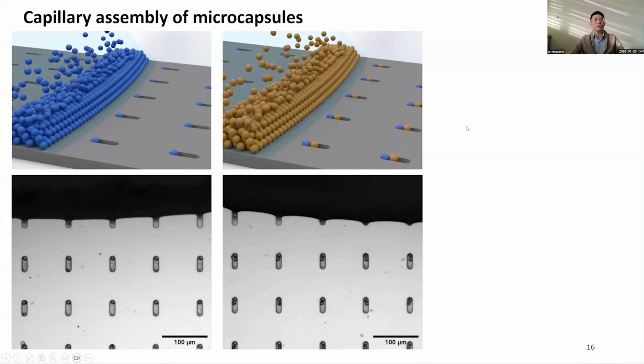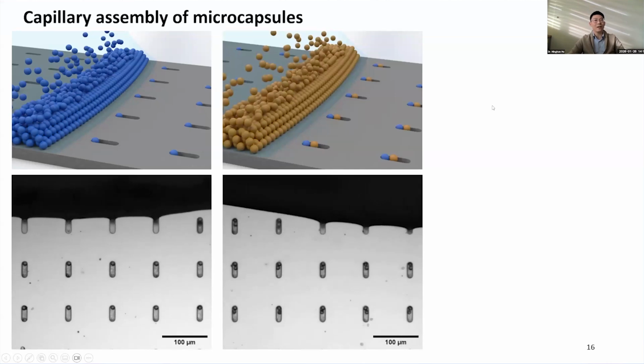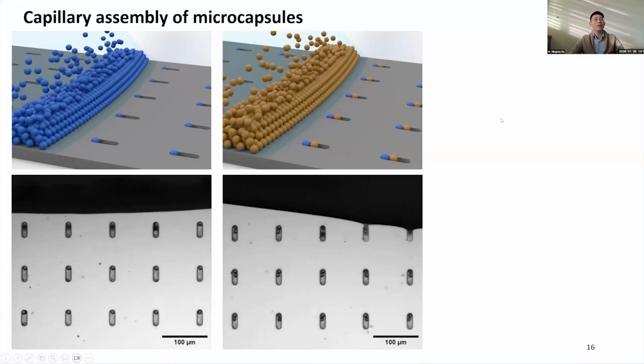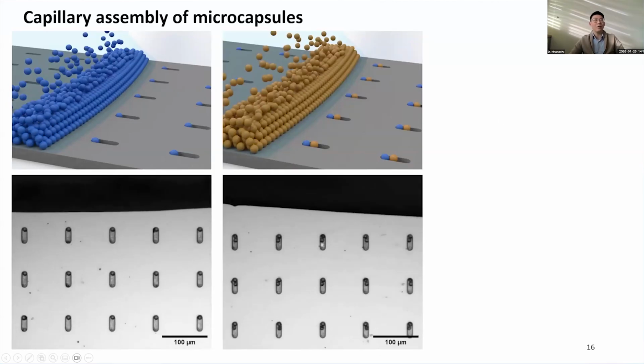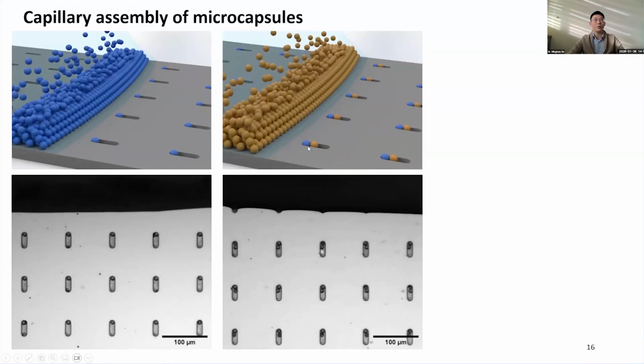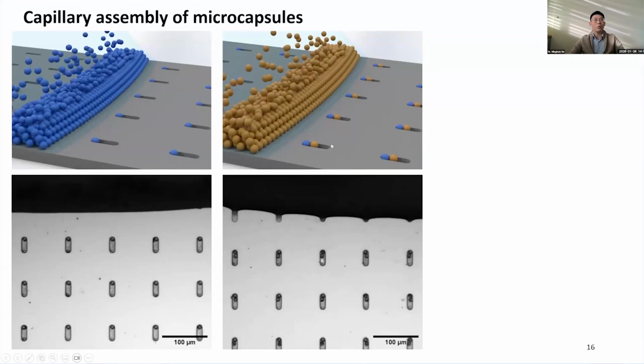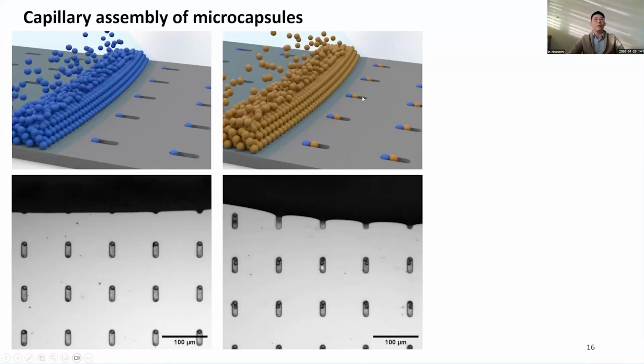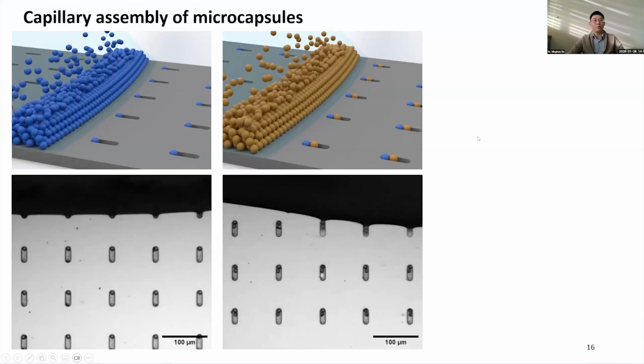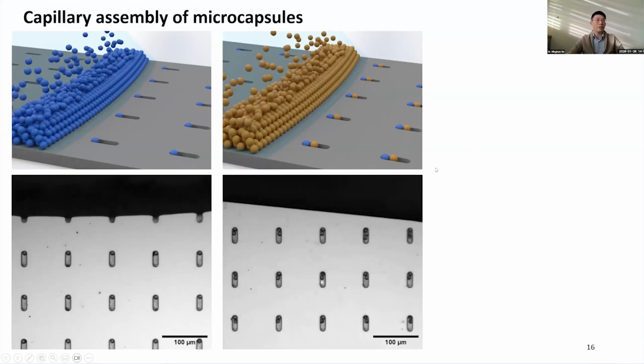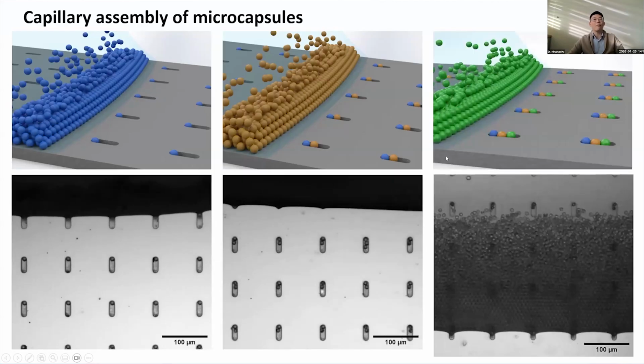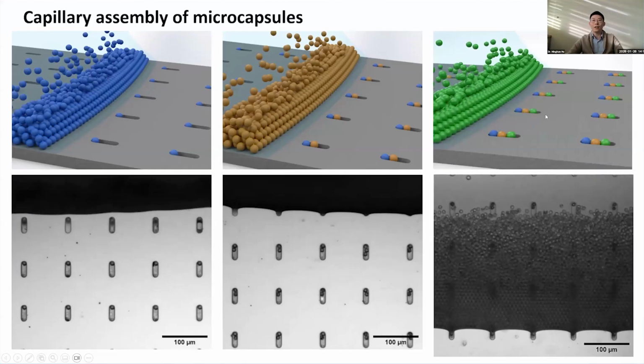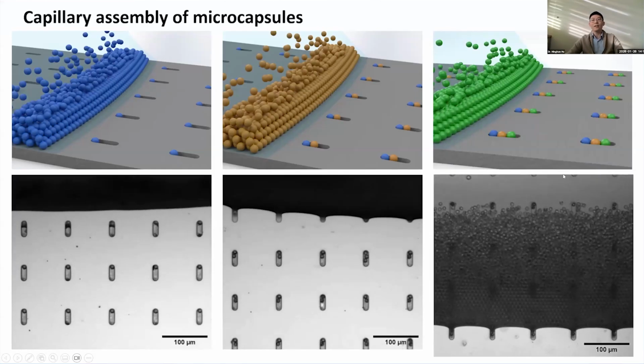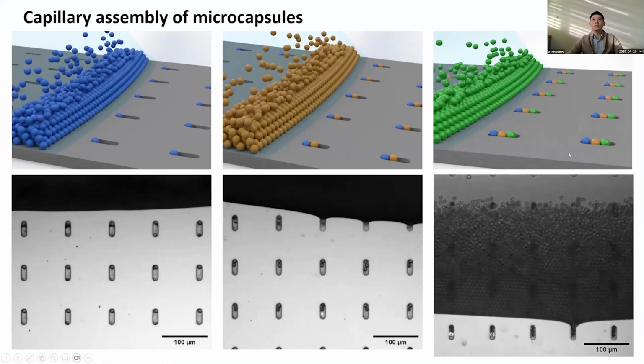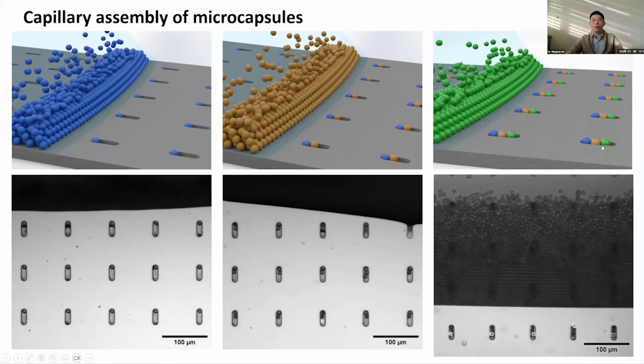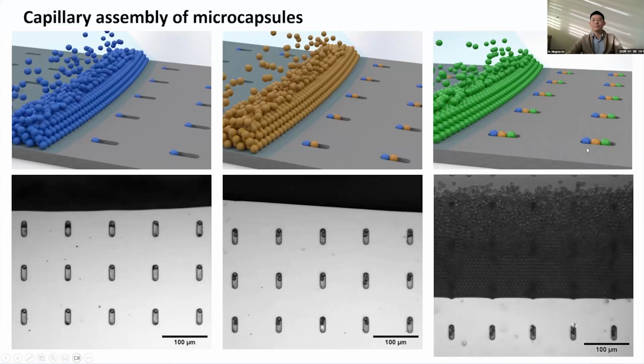And with that, we can let it dry, then we do the same trick again with another type of microcapsules. Then we can play around with the parameters to control it so that only another single microcapsule is deposited inside, as I show in this video and the schematic. And we do it again for the last one. So then we can have the 3 different microcapsules inside the traps.